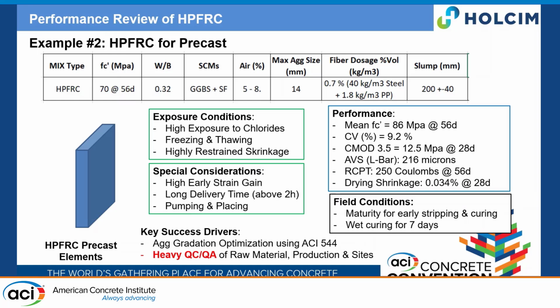The last one was a challenging one: a 70 MPa concrete with air, 5 to 8% air, with a combination of steel fibers and synthetic fibers for precast elements. Same thing, high exposure condition, high strength gain was also required, and the delivery time between the plant and the job site was about 2 hours. Because the concrete was pumped, the air void system was tested before and after. So this was the challenging part, where we had to babysit the site and the mix a little bit to ensure we have a very, very stable mix, especially when you have fibers. Same thing, we integrated maturity for early stripping with good curing practices, but a very heavy QC/QA on the process.